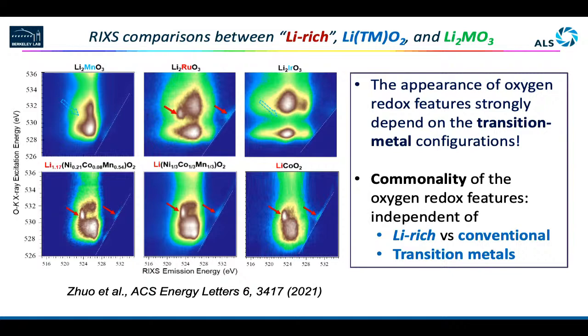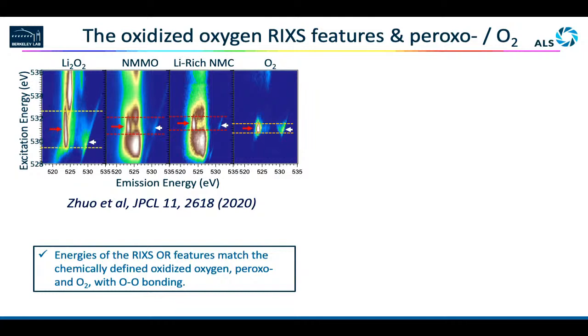If you highly oxidize an oxide, it will go to a different fundamental ground state, and it will change the overall configuration of the oxygen–transition metal. They all give you this opportunity. And if you look at different 4d and 5d transition metals, you will see the feature appear or not appear. This heavily depends on the transition metal, meaning it is more like a fundamental transition metal–oxygen topic instead of any structural type of choice here.